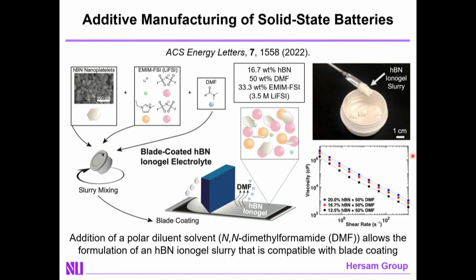And so most recently, what we figured out how to do is to achieve this same structure utilizing a traditional additive manufacturing, namely blade coating. It's a pretty simple fix. What you do is add a polar diluent solvent, namely DMF, that allows you to form an HBN ionogel slurry, which upon evaporation of the solvent leads to the strong gelation that I showed you before.